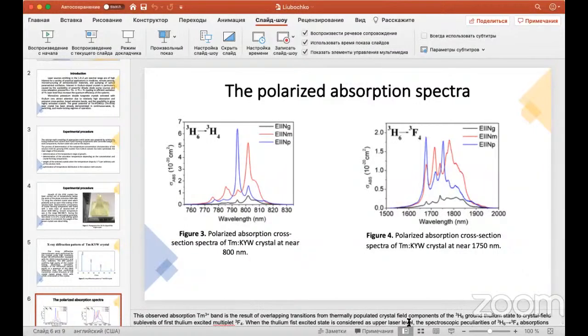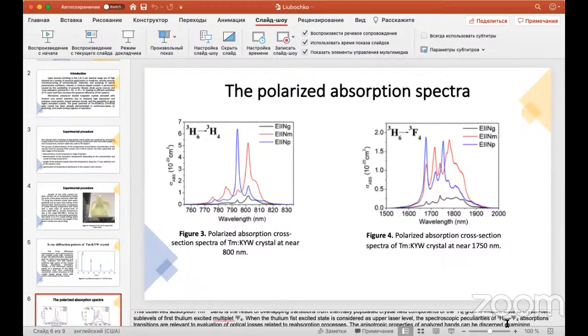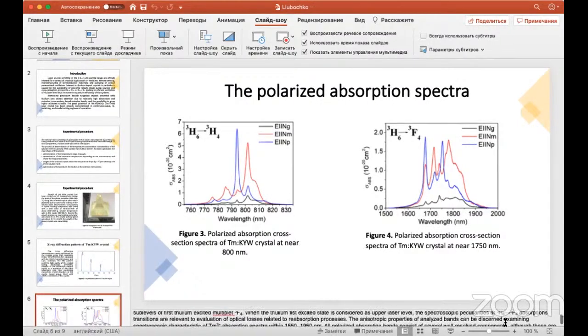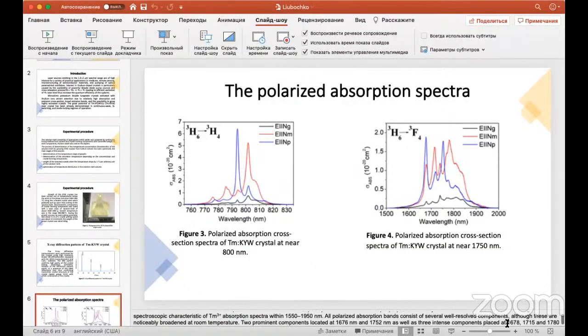The Tm3+ absorption band is the result of overlapping transitions from thermally populated crystal field components of the 3H6 ground state of thulium to sublevels of the first thulium excited multiplet 3F4. When the thulium first excited state is considered as the upper level, the spectroscopic peculiarities of the 3H6 to 3F4 absorption transition are relevant to evaluation of optical laser related processes. All polarization absorption bands consist of several well-resolved components. Also, these are noticeably broadened at room temperature.